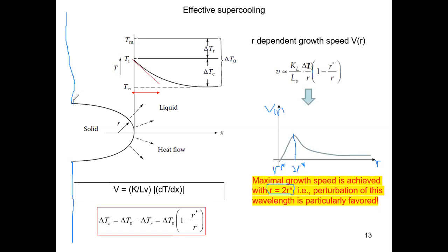The reality is that after you allow the initial nucleus to grow, the surface is going to transform into a kind of a bumpy thing like this. You're never going to have only a single nucleus, a single bumpy area. The whole thing is composed of many bumpy areas with different radius, everywhere. Because the fluctuations are occurring everywhere, it basically makes the interface very rough. You have regions with large curvature, regions of small curvature, right?